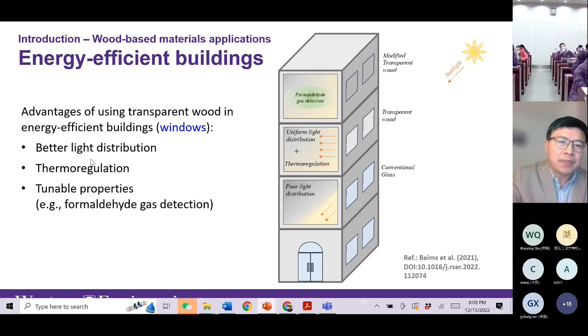They can provide better light distribution through this transparent wood-based material, and also can serve as a thermal insulation material. So they can regulate the temperature inside the room, and also they can be modified to get an additional tunable property, to add some functionality to absorb formaldehyde, and that's another application. So this makes the wood-based materials more useful than glass for window applications.